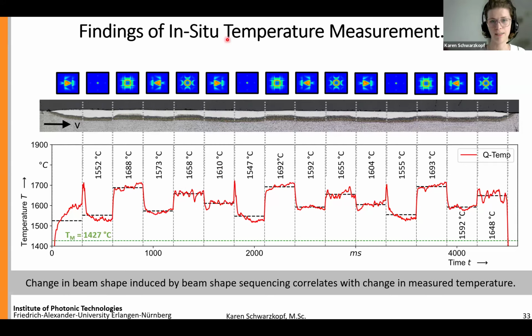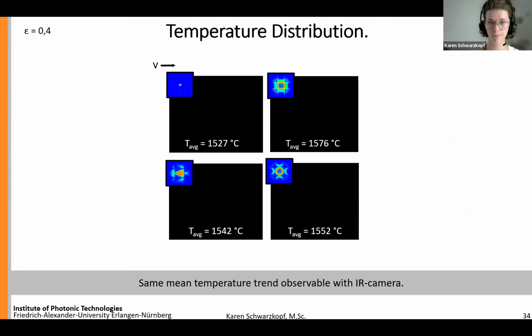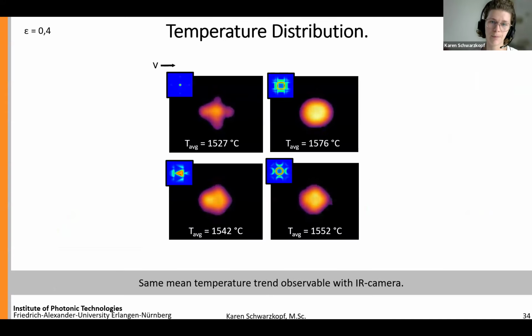Since the ratio pyrometer is relying only on a one-dimensional temperature profile, we also wanted to investigate how that really looks in the two-dimensional temperature field. And we did some additional temperature measurements with a thermal camera. And this looks like this.